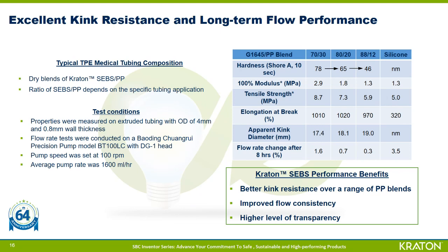Specifically for peristaltic pump application, consistency of flow over time is an important criterion. It may be an important criterion in other systems where tubing is used for long-term flow also. So here we performed flow consistency tests using a peristaltic pump, and we have shown the test conditions right here. We measured the flow rate before and after an 8-hour flow period, and we measured the change in flow rate.